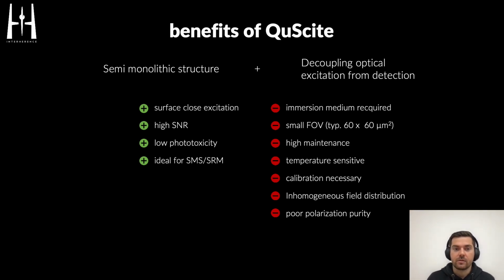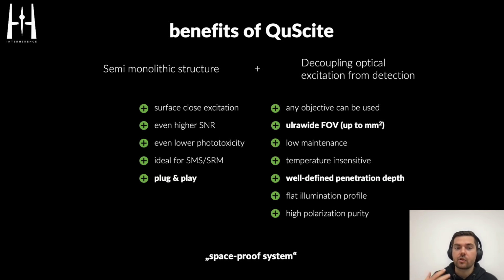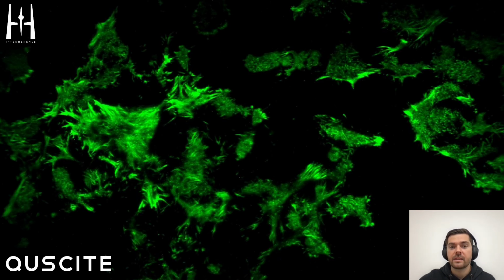And this in combination not only allows us to improve on the already existing benefits of TIRF microscopy, due to the very efficient excitation and no backscattering losses in the objective or low residuals, we have even higher signal-to-noise ratio, even lower phototoxicity, but simultaneously improve on all the shortcomings of TIRF. So you can now use any objective. It's ultra-wide field of view, low maintenance, temperature insensitive, well-defined penetration depth, flat illumination profile, and you generate a high polarization purity. And the system is plug and play. We like to call it a space-proof system. So that's a typical field of view where you have a single cell if you illuminate in standard, objective-based TIRF, but that's your horizon when you excite via QuScite.